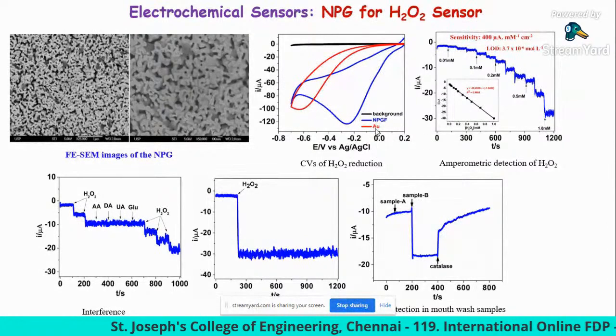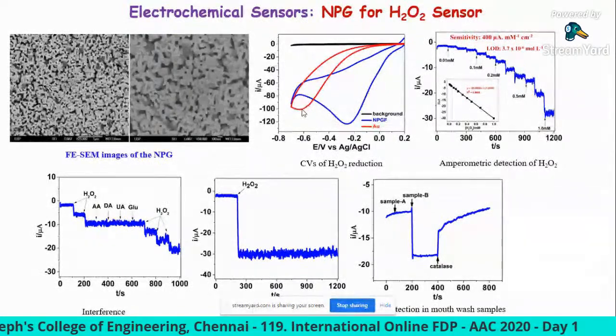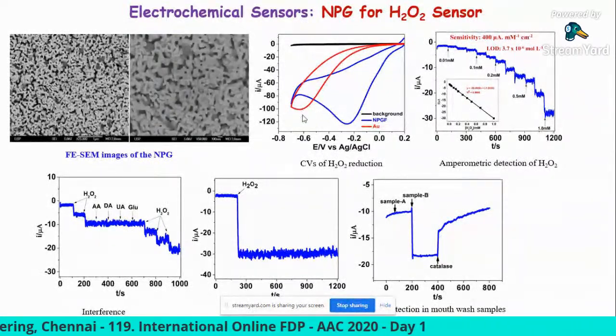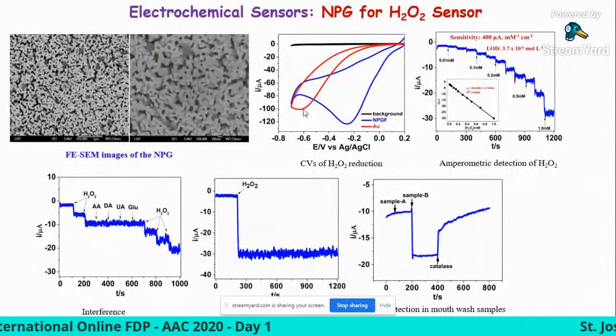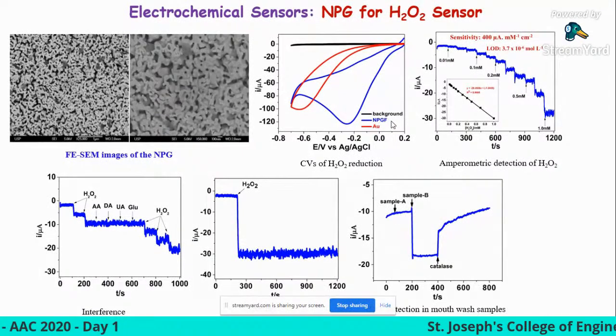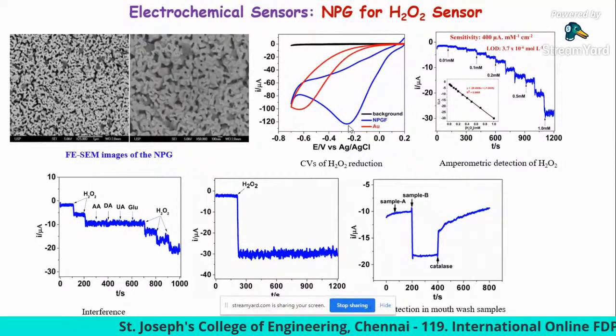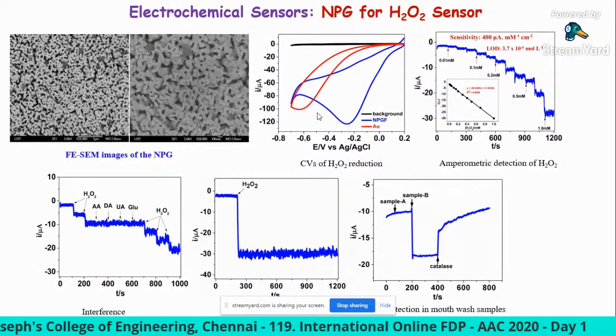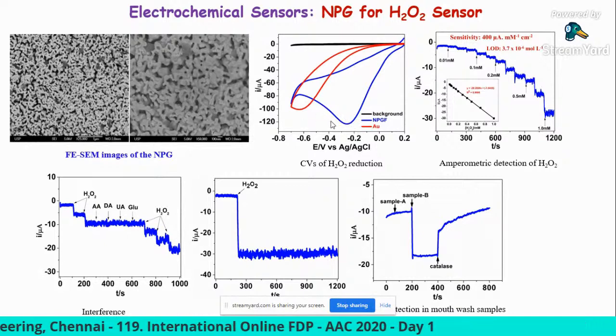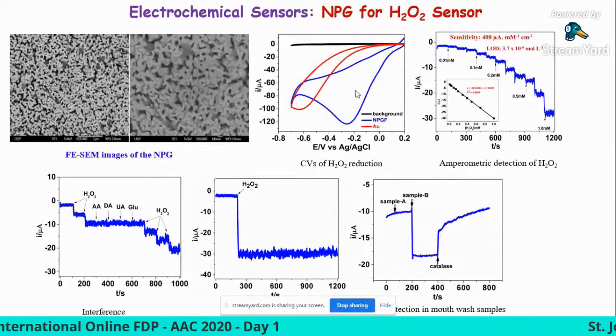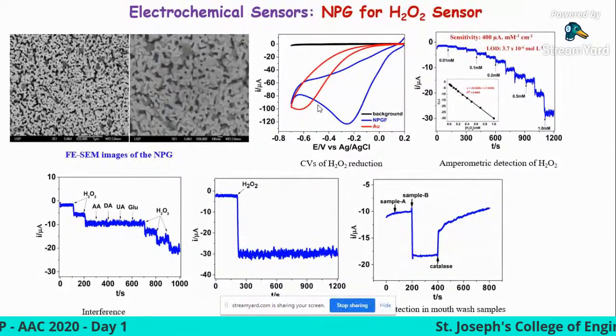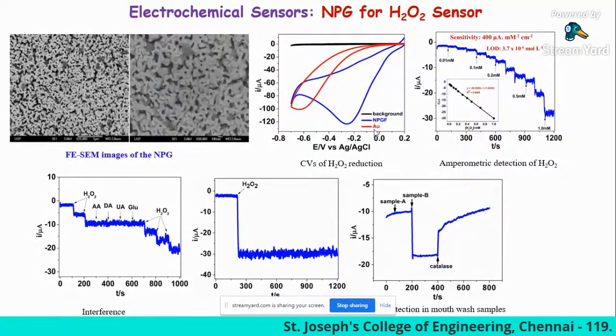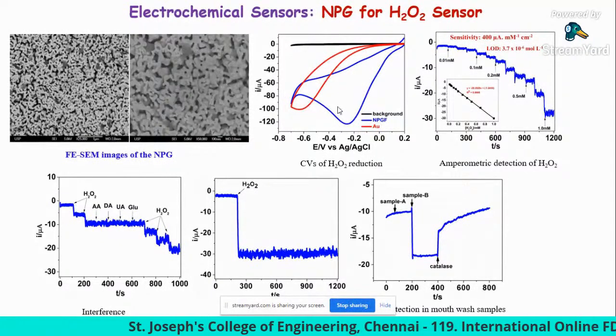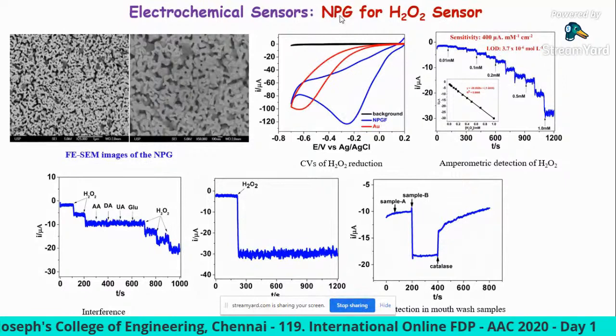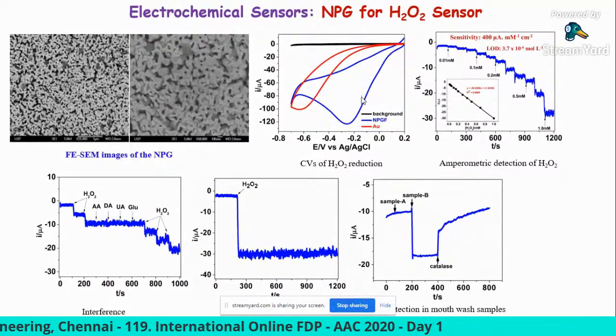For bare gold, the red line, the hydrogen peroxide reduction takes place at minus 0.6 volt. However, for the nanoporous gold electrode, the same process takes place at minus 0.2 volt. So almost around 400 millivolt, which is very high, shifted towards less negative potential, and the current signal also increases. This result shows the nanoporous gold is also suitable for hydrogen peroxide reduction.